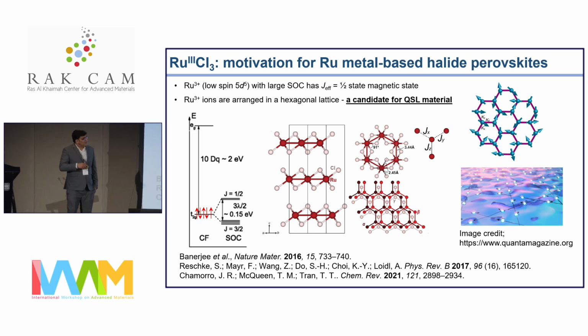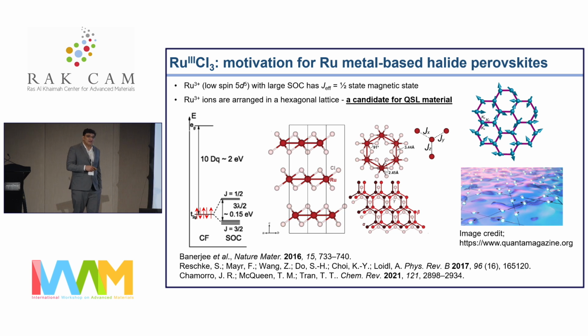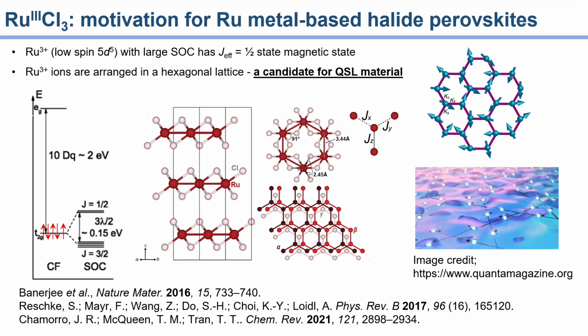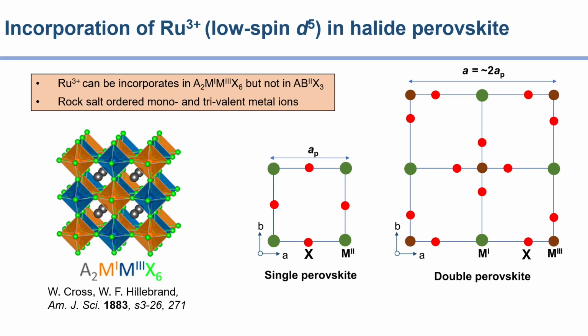However, there is a lot of interest in this material, but this phase is still not found in RuCl3. It typically orders antiferromagnetically at very low temperature. So a lot of work is ongoing in this area. But what we thought of is, because there are only a few known compounds of ruthenium halide, one of them being this, why don't we put ruthenium-3 in a perovskite lattice? And that's where the double perovskite comes into the picture.